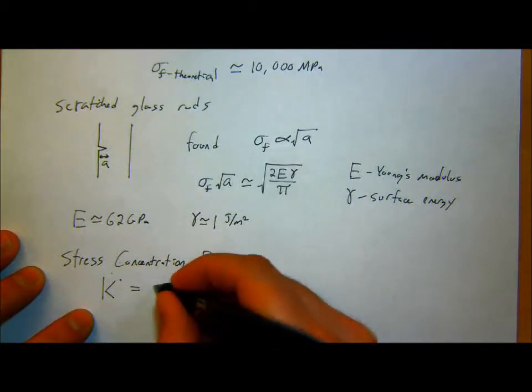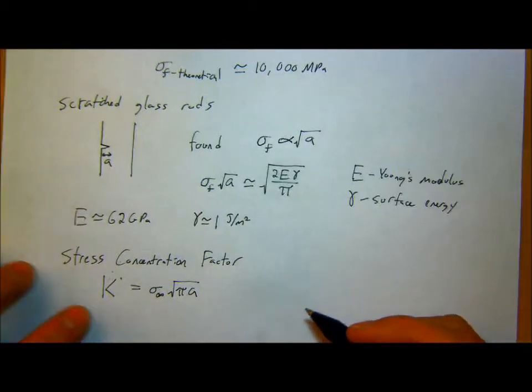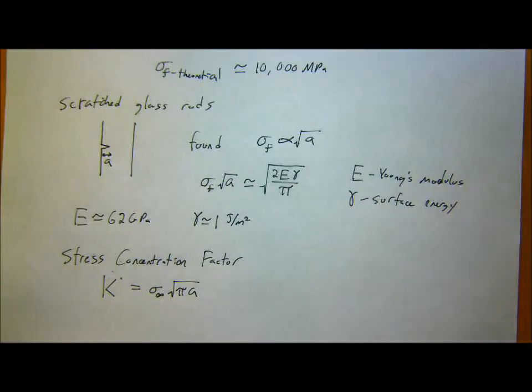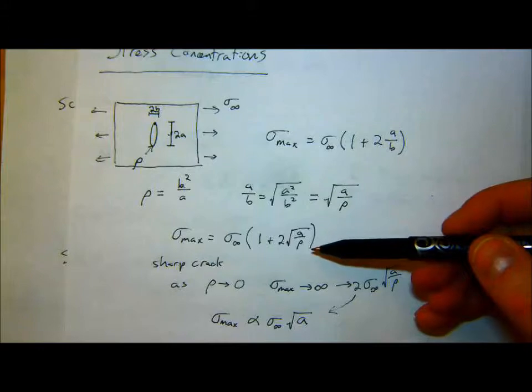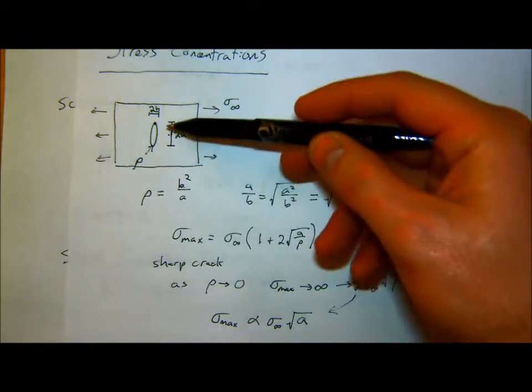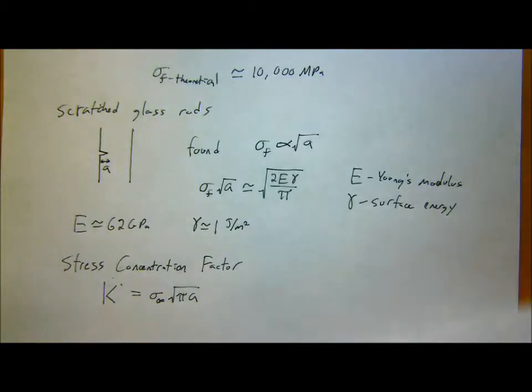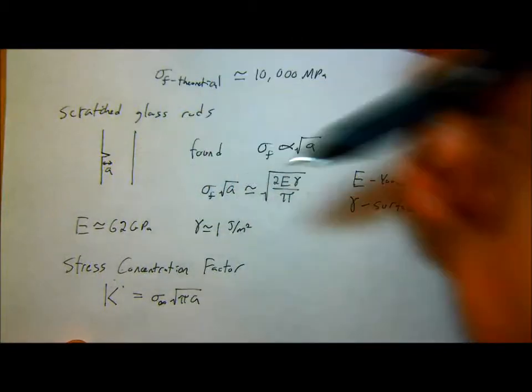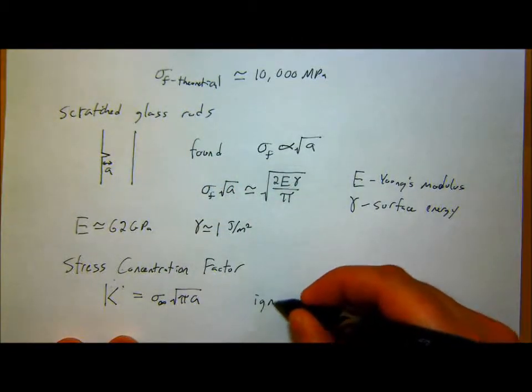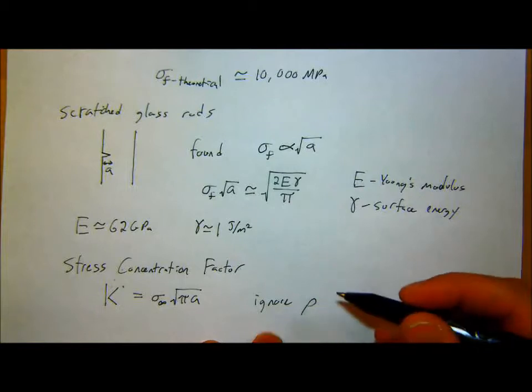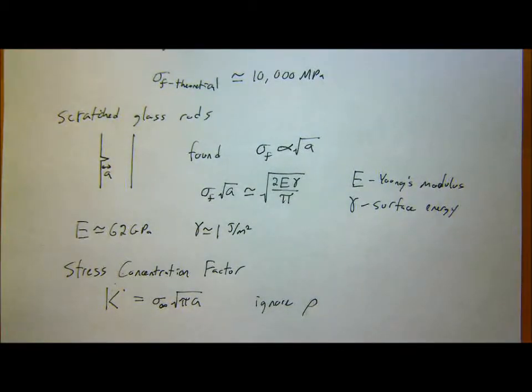So now I'm going to take this relationship that we had here, that maximum stress at the root of the notch, and instead think about it in terms of how that stress concentrates for a given crack length. So for this specifically, I'm going to ignore rho. Experimentally, it's pretty easy to see what the length of a crack is. You can see this thing internally in a material. I can make a measurement on a microscope with a ruler. But figuring out exactly what that rho is is kind of difficult.